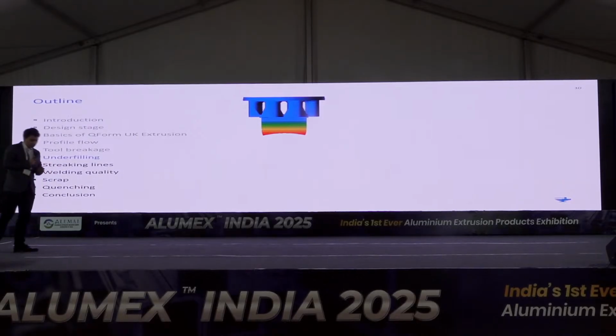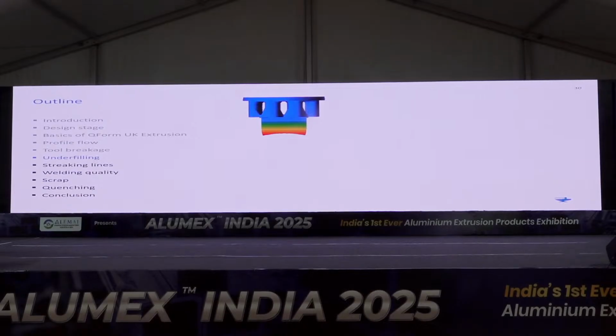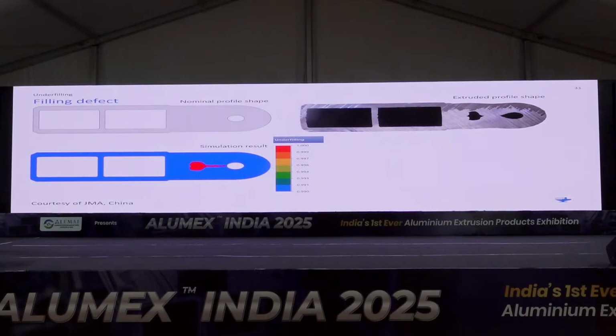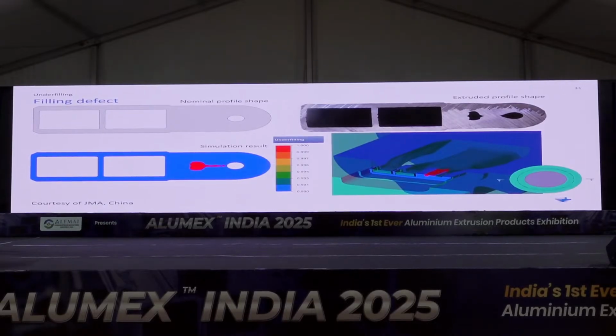So now let's consider several typical extrusion defects that can occur during the extrusion. The first one is the so-called underfilling defect. Here you can see the profile with a very different thickness in different areas. And here, unexpectedly, they end up with some additional cavity right in the center of the thick mass of the profile, which is not a good result at all. If you look deeper, we will find the reason under a particular bridge.